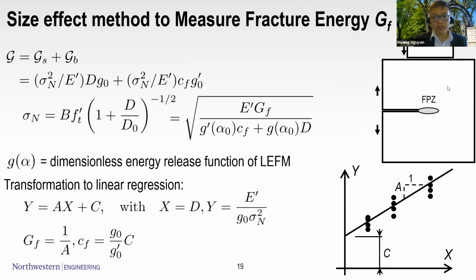So how to do the size effect method? The size effect method is based on the basic assumption that the FPZ of the material is a constant, has a constant area or constant volume. And when you scale the specimen to a bigger size, that domain, that area or volume does not change.